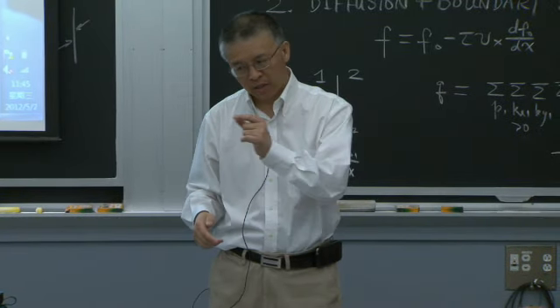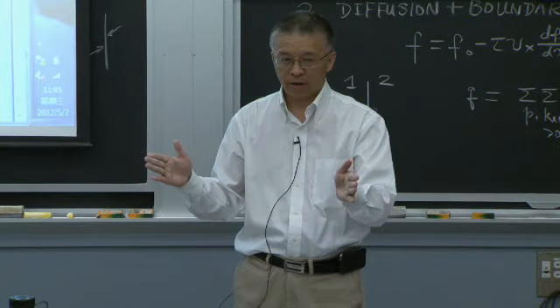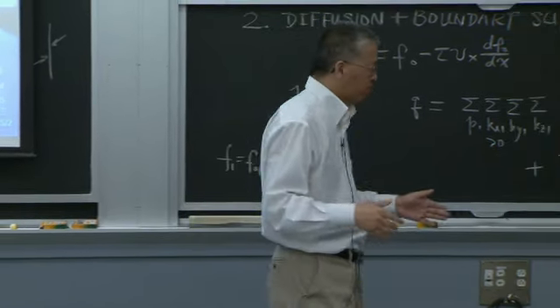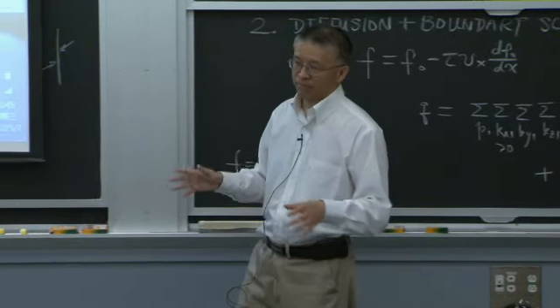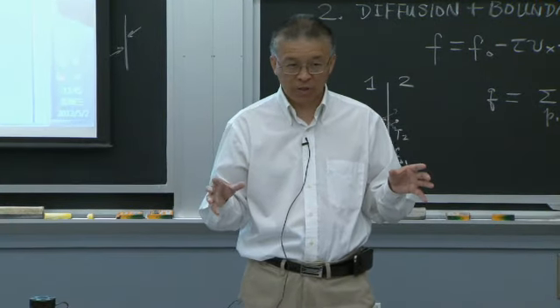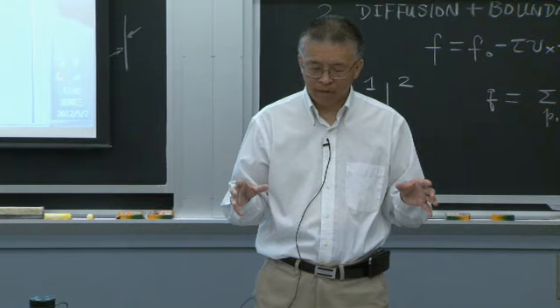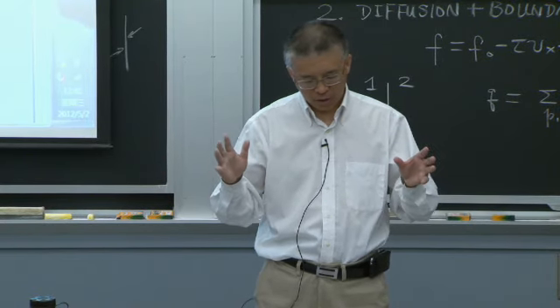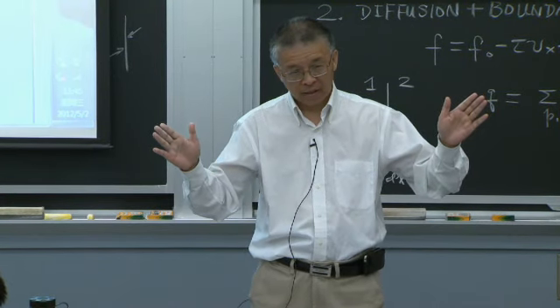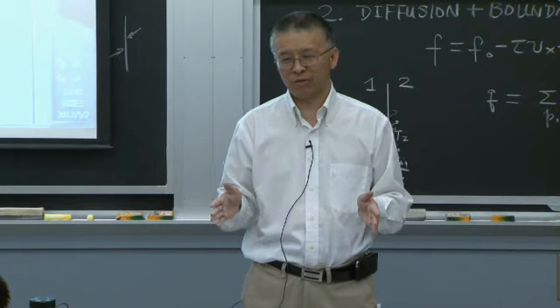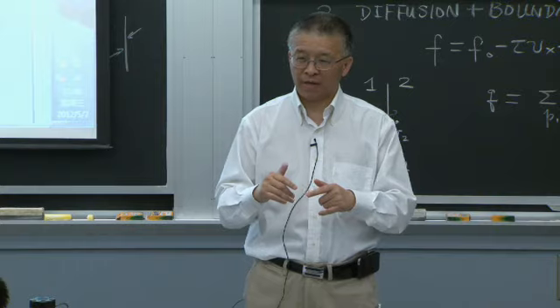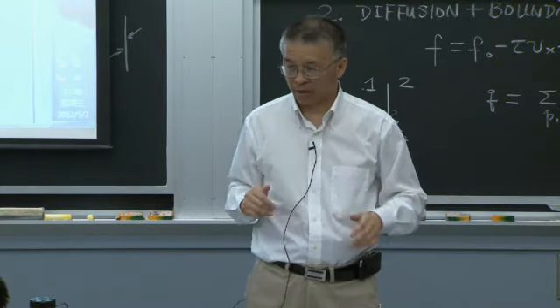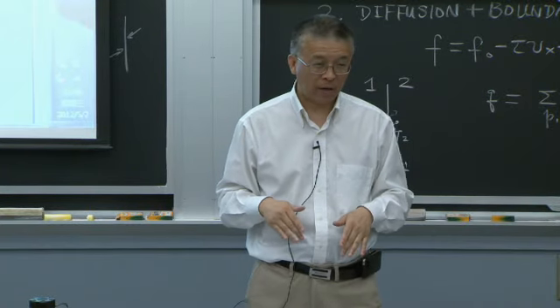And again, you have to be aware of what exactly you're measuring. In the case of electrons, for example, you have a metal-semiconductor interface. You put an electrode there. You will not be measuring the voltage exactly at the interface. You're actually measuring an average over that metal. It turns out I checked a lot of papers in electrical engineering. People do thermionic emission modeling. Of course, thermionic emission cases differ. Some people do it for a layer inside the device, and in that case I see most of the papers actually use, to me, a wrong formula, because their formula will not approach the limit when there's no barrier between the layers. For electron transport, it's the potential barrier at the interface.